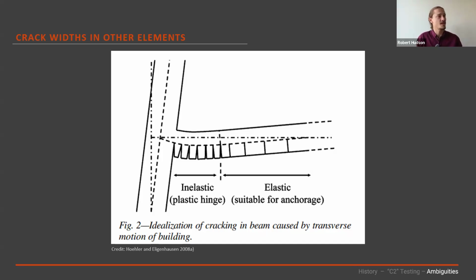Now, there is published justification for where the 0.8 mil crack width for C2 capacities comes from. It's from a research study that I've got a screenshot from on the screen. I think I mentioned this at the beginning. It's basically looking at the elastic portion of a reinforced concrete beam, minimally reinforced, pretty standard size. You load it, and when you start getting yielding in your reinforcing bars, they used predictive crack width equations to estimate that the crack width at that point would be 0.8 mils.